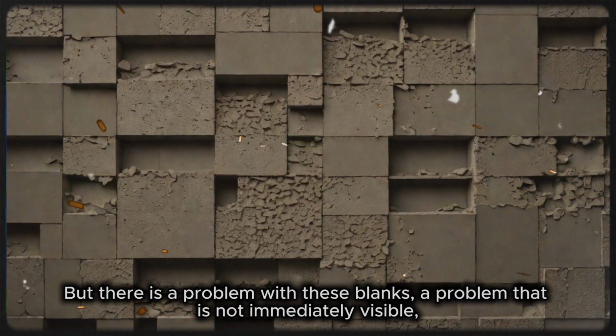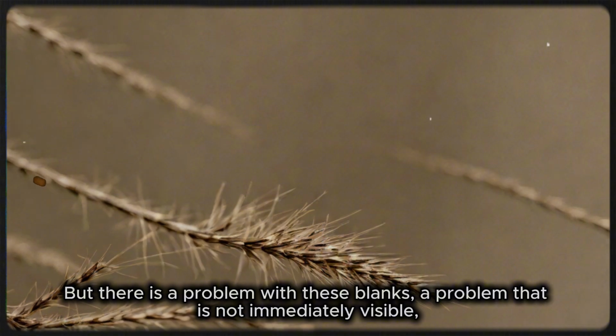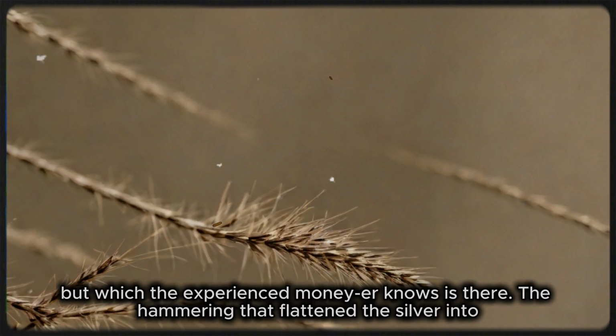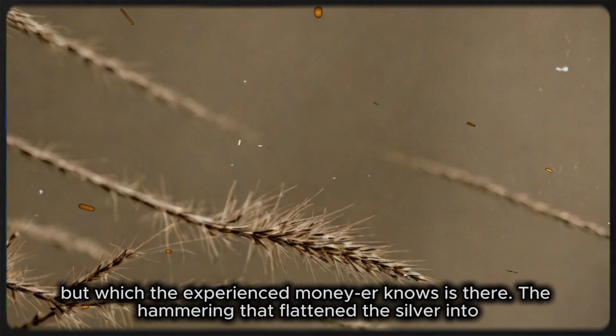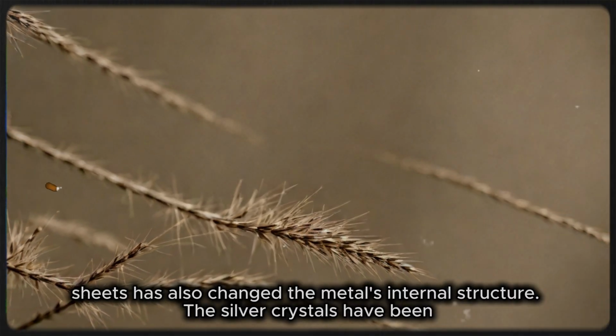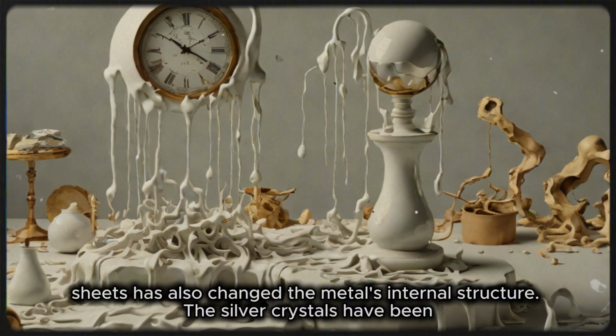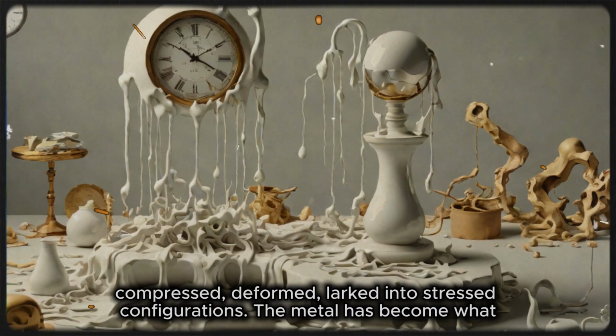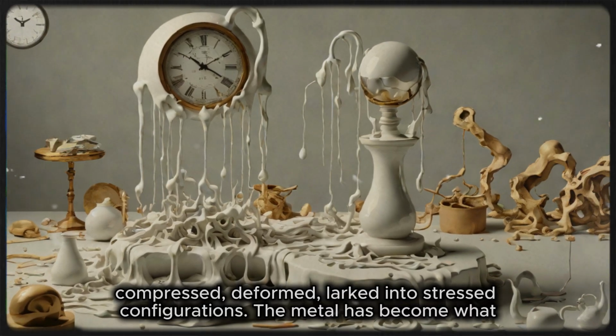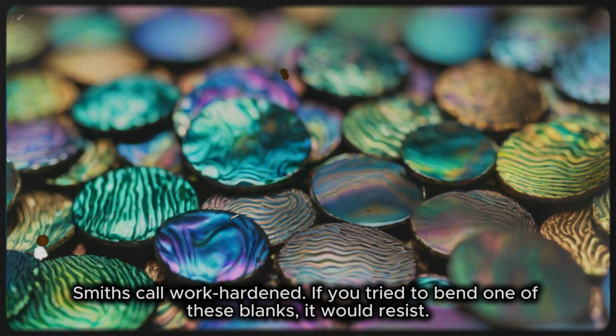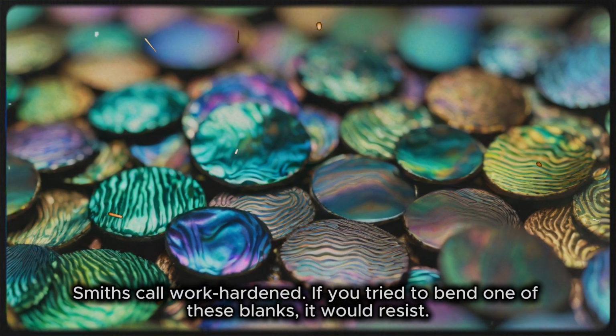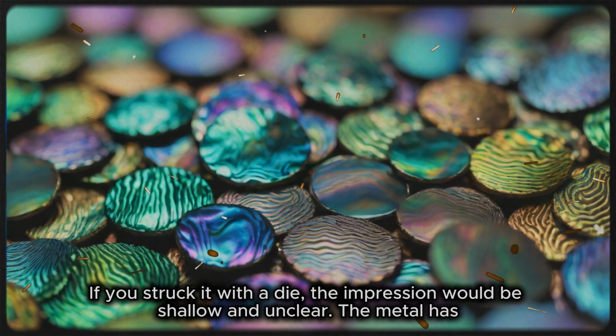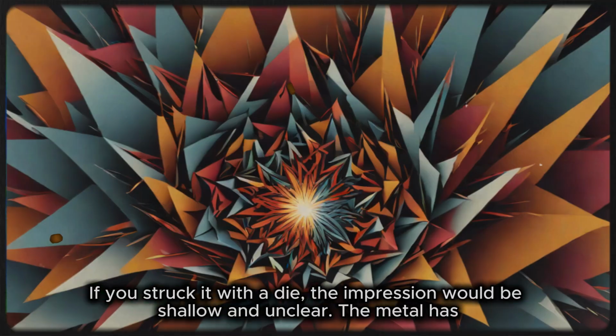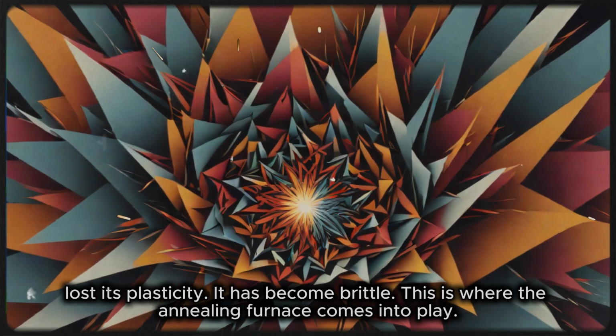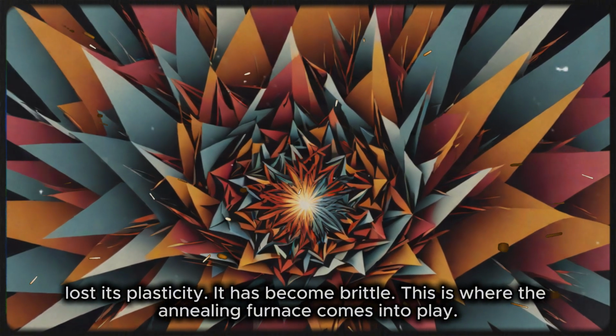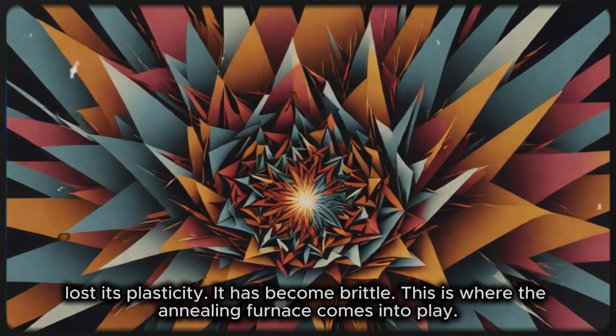But there is a problem with these blanks, a problem that is not immediately visible, but which the experienced moneyer knows is there. The hammering that flattened the silver into sheets has also changed the metal's internal structure. The silver crystals have been compressed, deformed, locked into stressed configurations. The metal has become what smiths call work-hardened. If you tried to bend one of these blanks, it would resist. If you struck it with a die, the impression would be shallow and unclear. The metal has lost its plasticity. It has become brittle. This is where the annealing furnace comes into play.